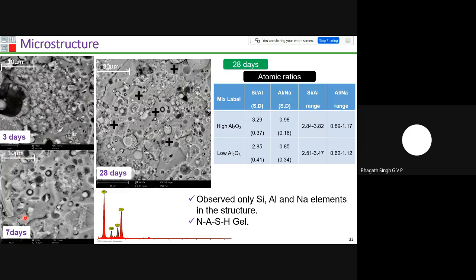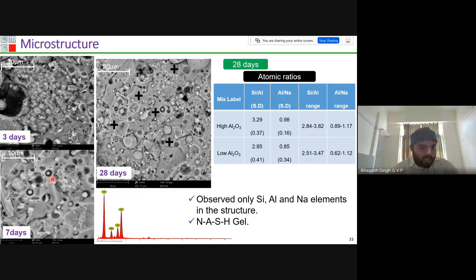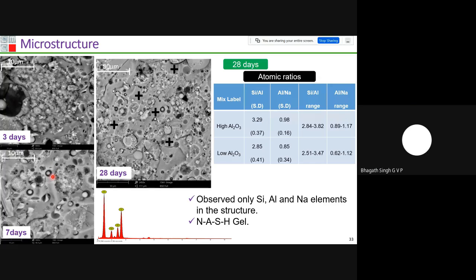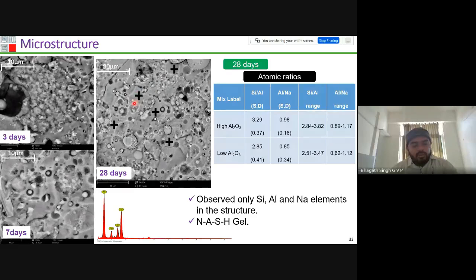But in the case of 7 days, you can see the cenospheres are completely dissolved, and for some of the cenospheres, you can look here, the sphere is dissolving and the product is forming around the cenosphere. And almost completely dissolved spheres I can observe at 7 days. But in the case of 28 days, we can see a dense product over the image, and I have observed almost completely dissolved cenospheres over the image.